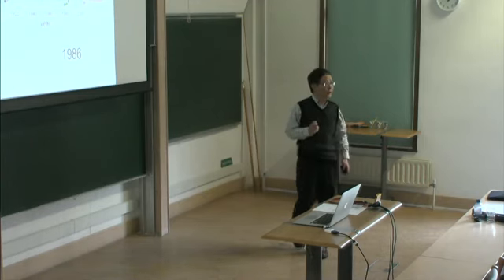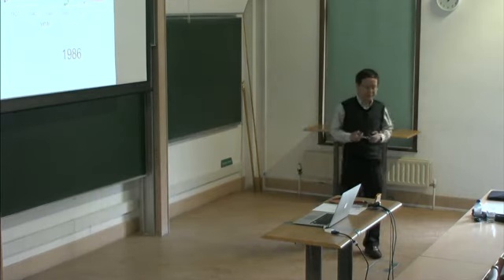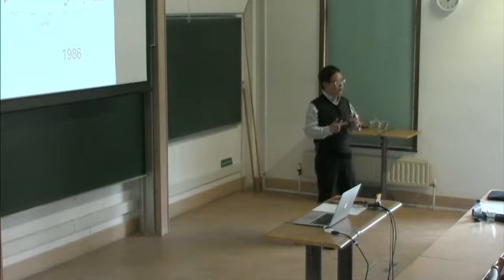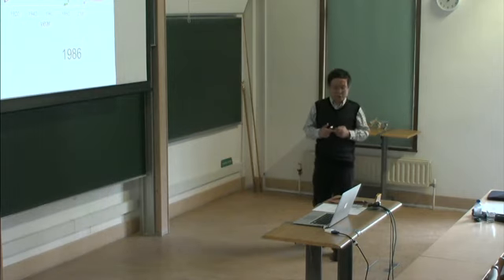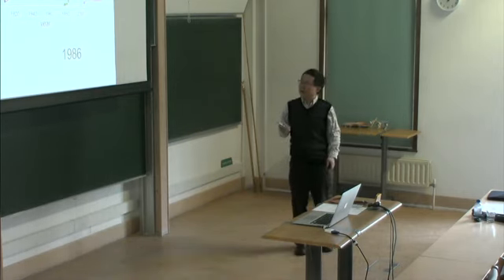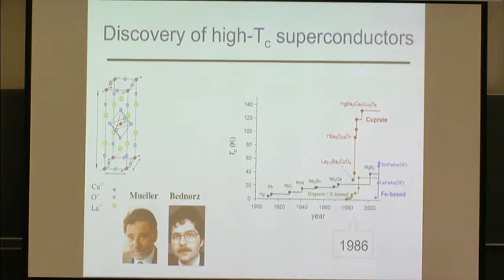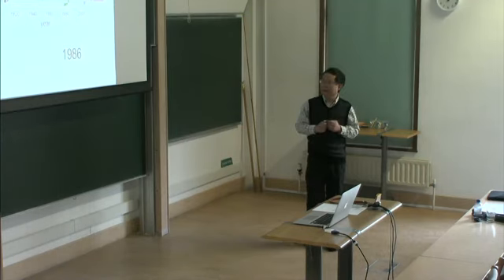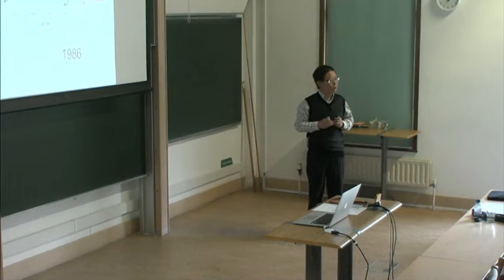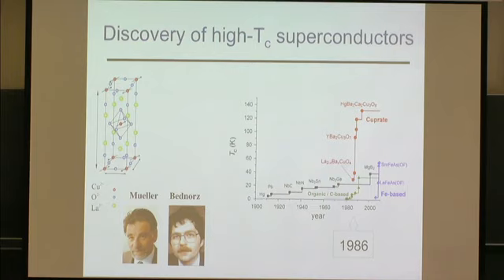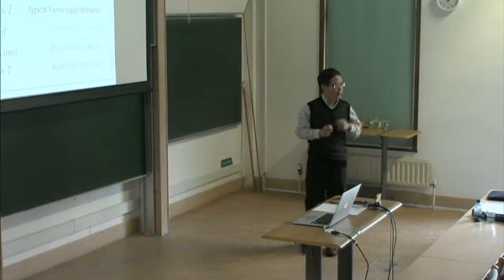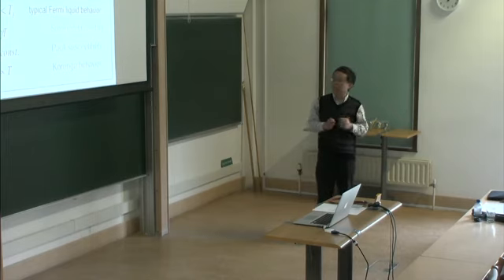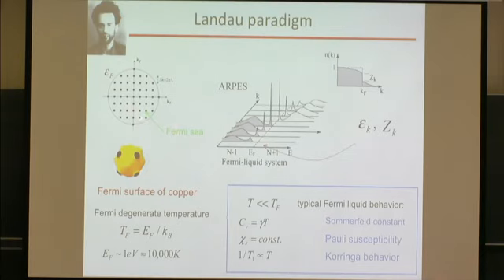So the big question here is whether these new superconductors, cuprate superconductors, are still described like BCS superconductors, or they are some new state of matter. And the related question would be that for a conventional BCS superconductor, when the temperature goes beyond the critical temperature, you will get a so-called Landau Fermi liquid state. But the cuprates have quite dramatically different behavior above the superconducting transition temperature, especially at low doping. For the Fermi liquid case, basically electrons fill up the Fermi sea, and the low-lying excitations happen around the Fermi surface, which will contribute some typical Fermi liquid behaviors.